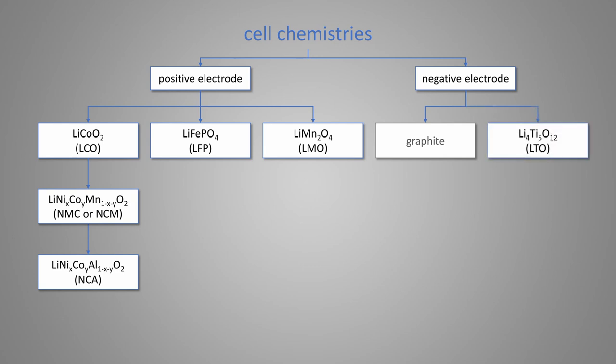There's one exception however, which is lithium titanate oxide, or short LTO, that is used on the anode side. This anode can be combined with various different cathodes, so just naming it an LTO cell is not completely correct. LTO as an anode material has some advantages and some drawbacks. The biggest advantage is that it's very stable, so it has a very long lifetime and it also can be charged very quickly. That comes with the downside of having a much lower cell voltage compared to graphite based systems, which reduces energy density and basically disqualifies it for all applications where you need high energy density. So it's really a niche chemistry for applications where you need fast charging times, maybe high currents in discharge, but with less capacity and energy inside.